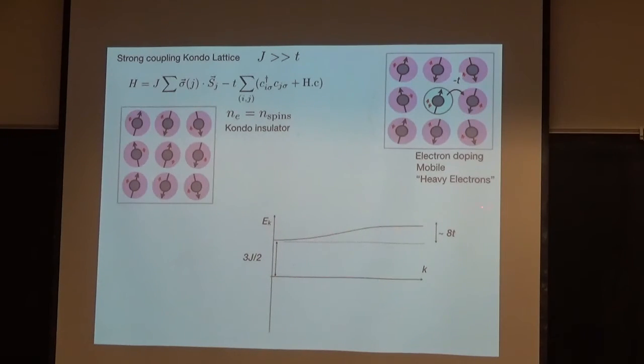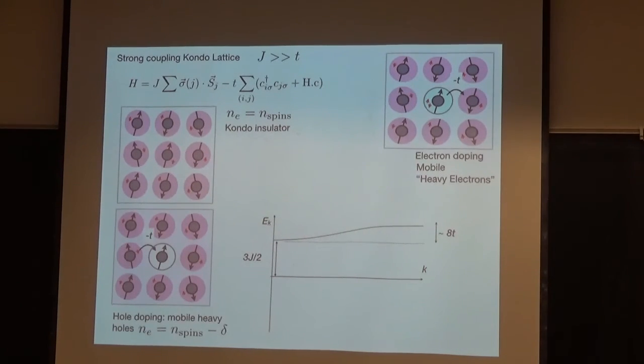This is a hole-doped heavy electron state. Interestingly enough, if you think about that, it's rather similar to the case of the cuprates. The cuprates can be thought of in some sense as a very large J heavy electron problem, of course, in which you drained out almost all of the electrons. So here, you can also pluck out an electron, that's hole doping. You then have a mobile hole, and that then forms a state which we put down here.